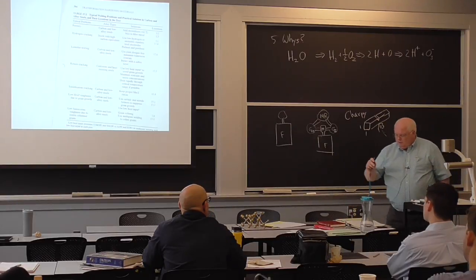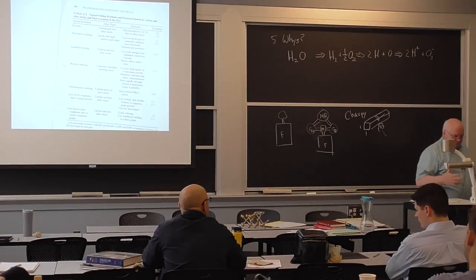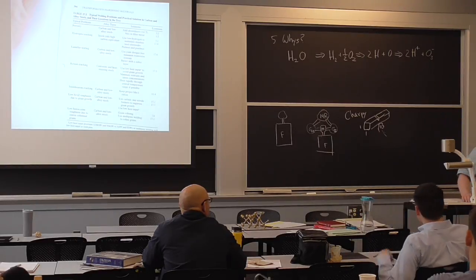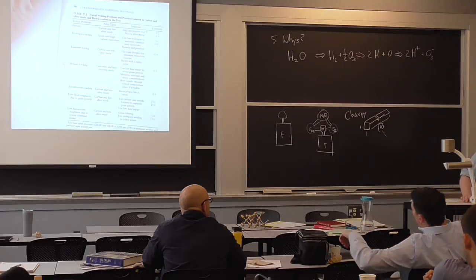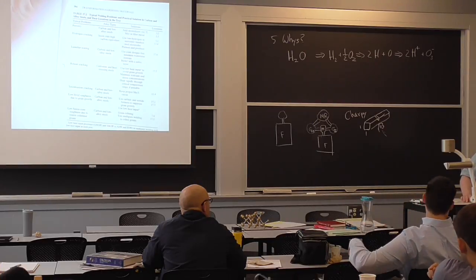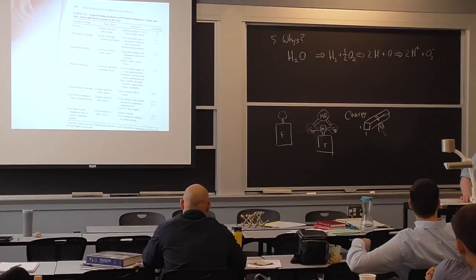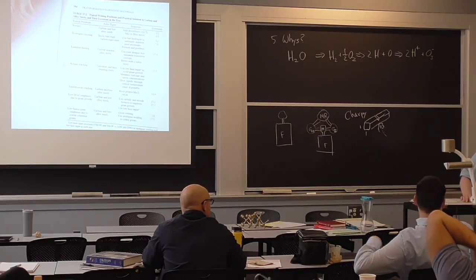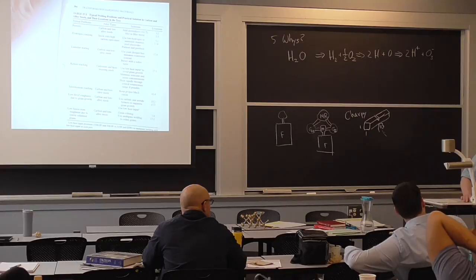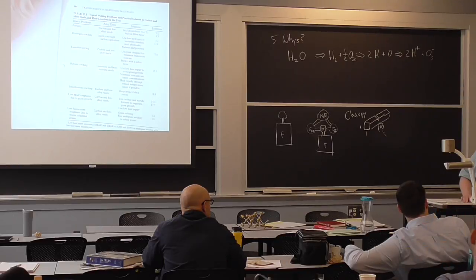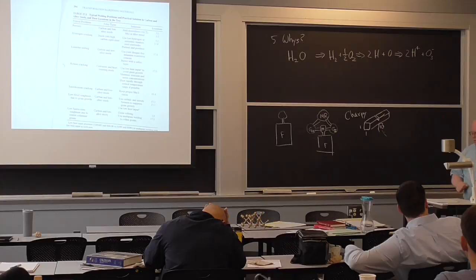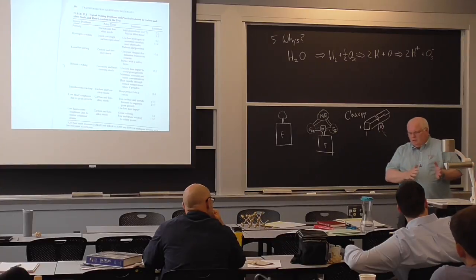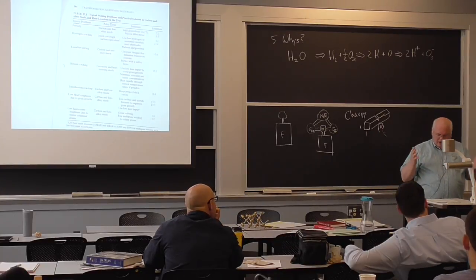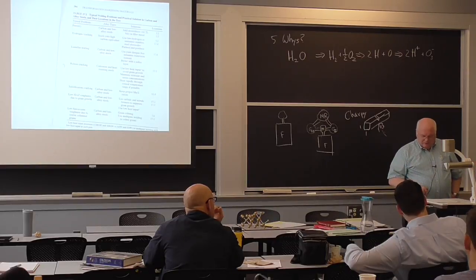In any case, what happened with these Charpy tests? Well, in the 1950s, the Navy said, okay, after the report came out in '46, it took a while to digest it, they said, okay, we're going to require 15 foot-pounds. We're not just going to require a tensile test on our steel. We're going to require 15 foot-pounds of Charpy energy. And we're going to require it at the weld because a lot of these things are found in weld defects. Okay, so base metal, weld fusion line, weld metal, we're going to look everywhere we can.